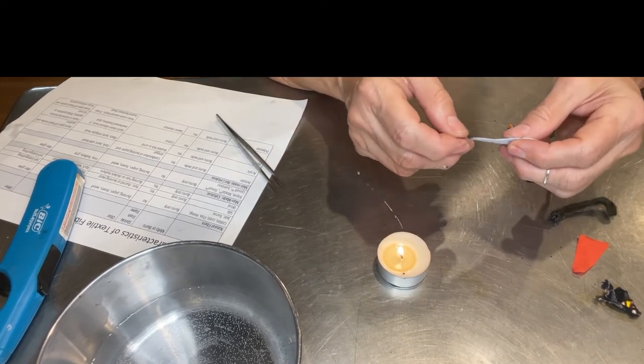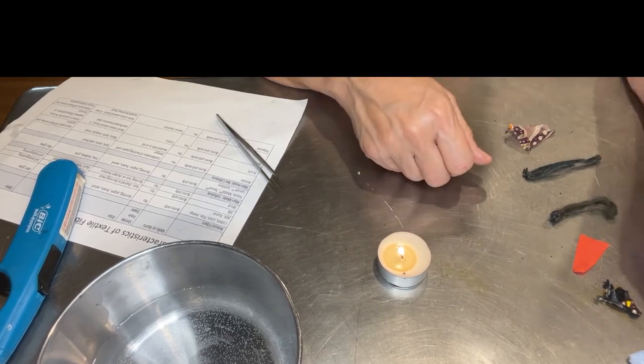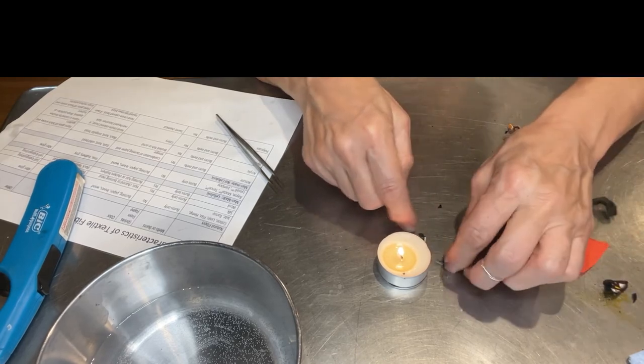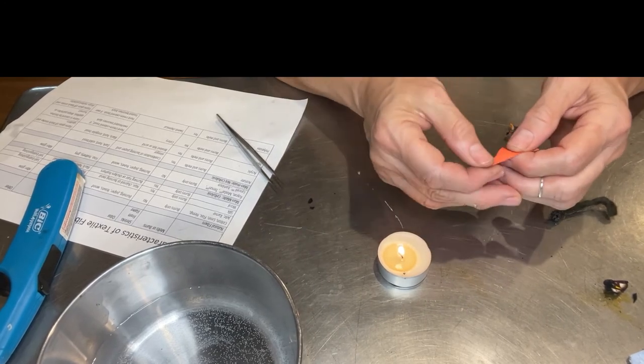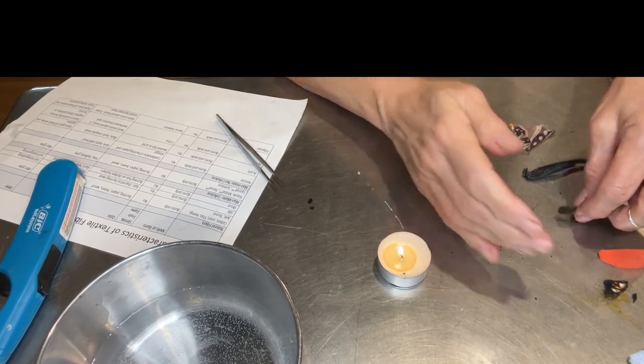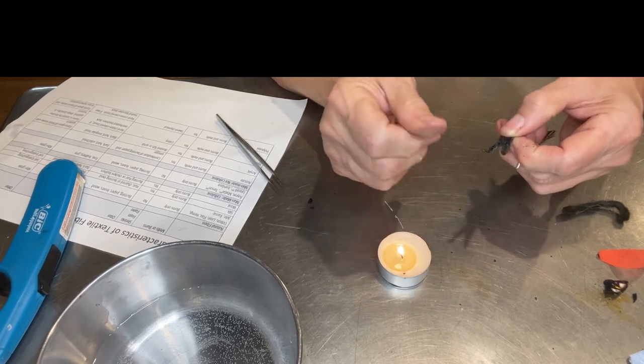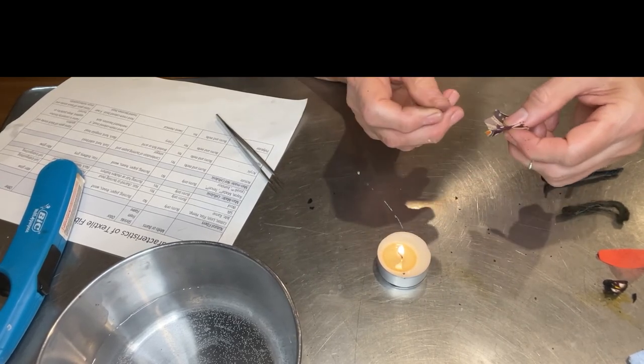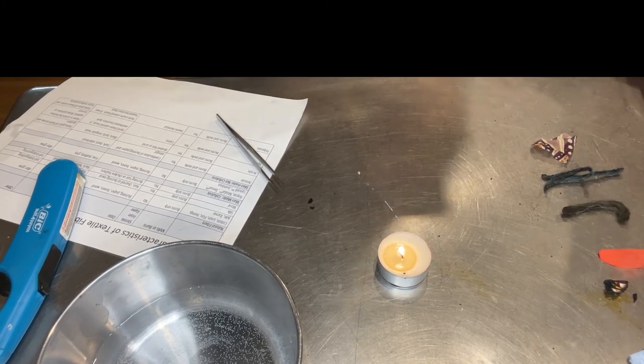Let's check these. This one has a soft bead that's crushable — I think it's a blend of poly and maybe some paper or something. This one is completely crushable — that was definitely cotton and smelled like wood. This one smelled sweet and chemical and has a really hard bead — that's the synthetic blend. This one smelled like burning hair with a crushable bead — that's wool. This one is all synthetic, acrylic and nylon I think — part of it crushes and part is like melted plastic. And this has a crushable edge with no bead — that's silk. I hope this helps and I hope you have fun burning your fabrics — please don't burn your house down!